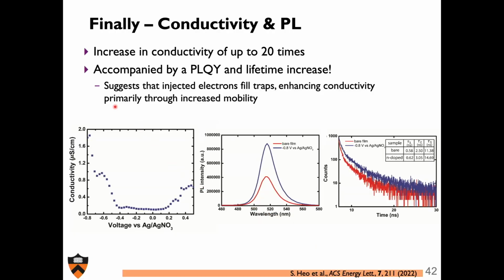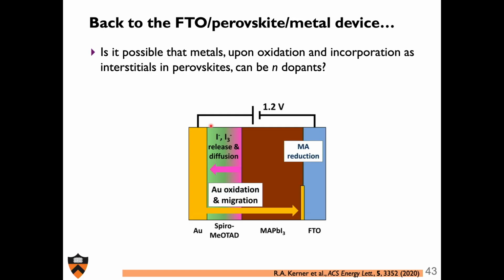And so what we suggest, it's hard to know, but what we think is that the injected electrons are actually filling traps, and our increase in conductivity is actually more or less an increase in mobility, because we're basically making the system a better electron transporter. We're not actually adding free electrons to that system. So back to square one. It's really hard to dope these systems.